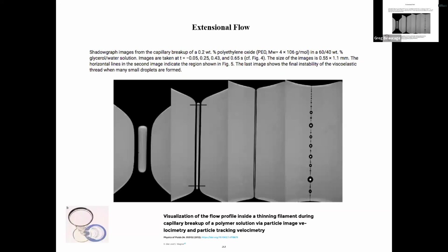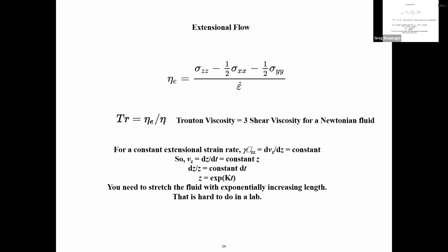Anyway, when you do that kind of measurement, it's called extensional viscosity. It's kind of like when you take chewing gum and pull it, right? That measurement has a technical problem. If you want a constant strain rate, a constant drawing rate of something, you have to draw it exponentially increasing in time. You start out slow, and eventually you have to start really running fast with it, and then put it onto a rocket at some point to get a constant draw rate, right?